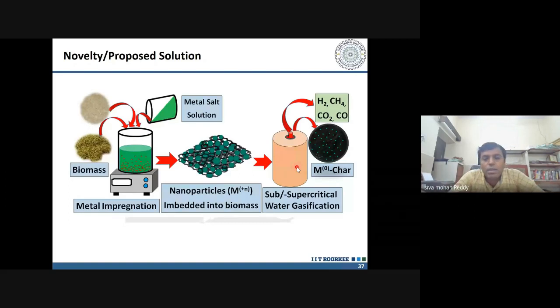Okay, so this is the process that we have implemented, or developed, in our lab to make sure that we generate the nanoparticles inside your biomass matrix right at the front end itself, and then subject these nanoparticle embedded biomass to sub and supercritical gasification to yield a hydrogen rich gas mixture and nanometal carbon hybrids. Okay, so typically what happens, we choose any kind of biomass, take it, and grind it into powder or maybe paste.